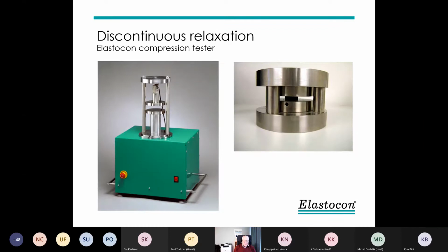We at Elastocon developed a similar instrument, but we had found that there were some important factors. And one was to compress the sample to exactly the same compression every time. And we made this, we called it a compression tester, and there we could compress the samples within 1/1000 of a millimeter, the same every time. Then we could get more repeatable results. But we have discontinued making this because there is very little request for it.